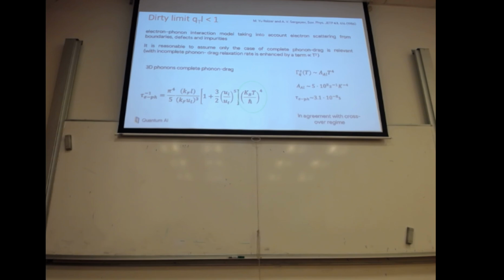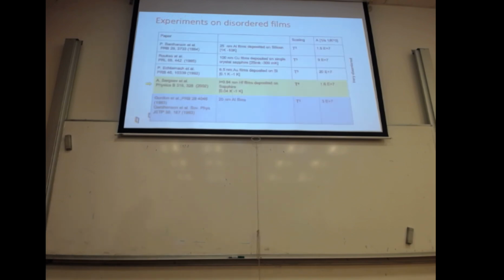And what I see is that in the case of the dirty limit, what I would expect, according to this theory, is a T4 dependence of the temperature. And there is some consistency in these two estimates, because when I go at the crossover, I find the same value of the relaxation time that I would have in the clean limit. But then I trust theory, but I wanted to look also at what is going on from an experimental point of view.